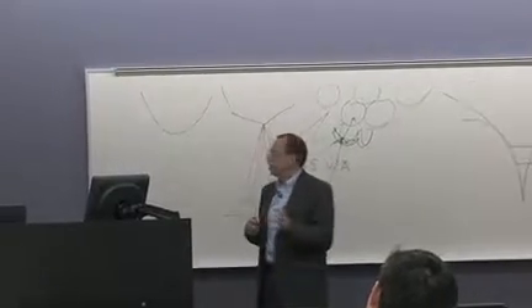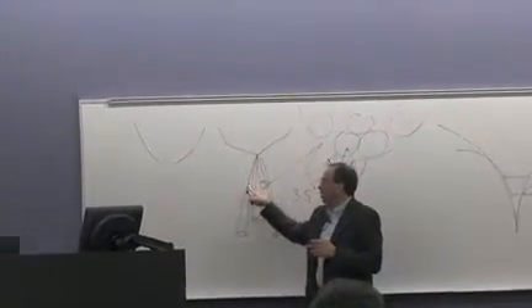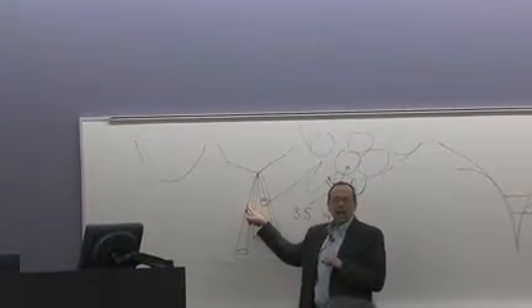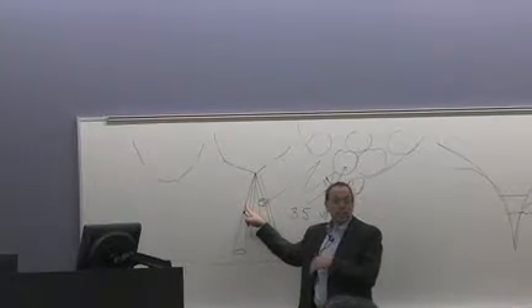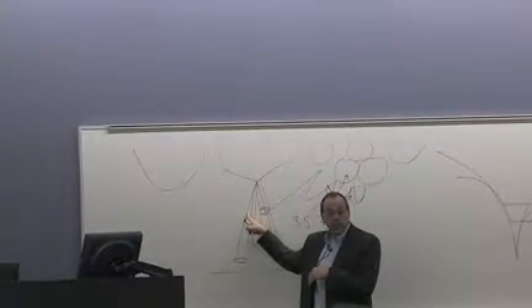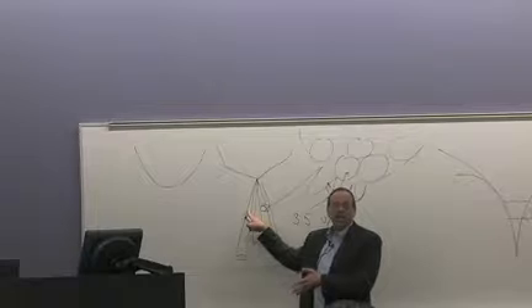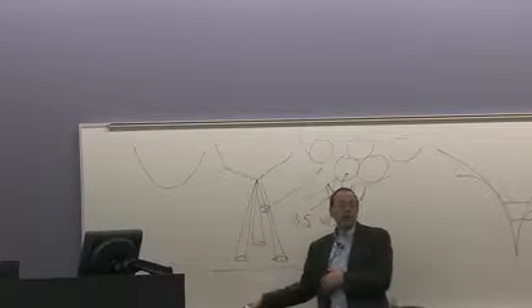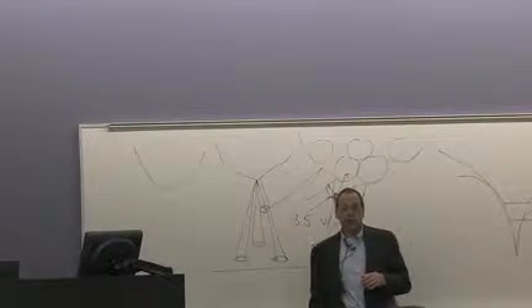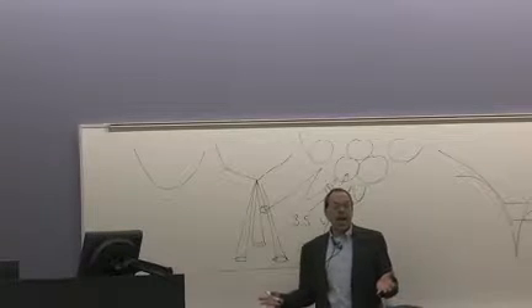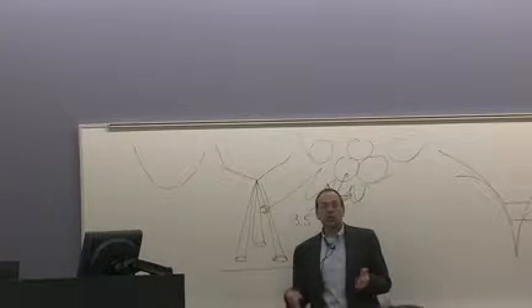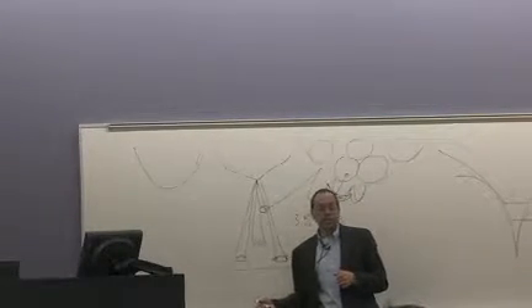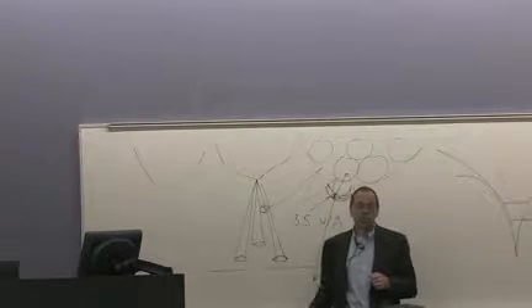And the mechanism there is you create a helium ion up here, but it can have a close encounter with another gas atom, and it could steal its electron. So it's going to continue on. Even though it's aiming at going on at 30 keV, it can get neutralized, and it goes on at 30 keV. Fortunately, those ones don't get focused or scanned, so they don't add anything meaningful to the images. But there are some neutrals, typically a very small percent, but unfocused.